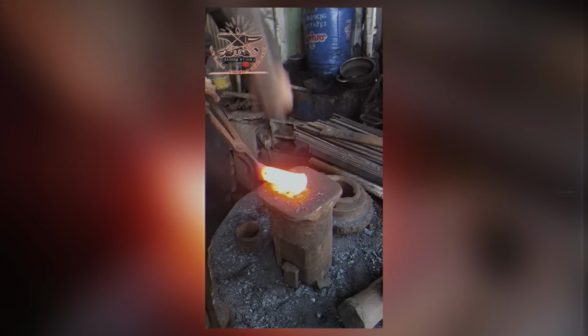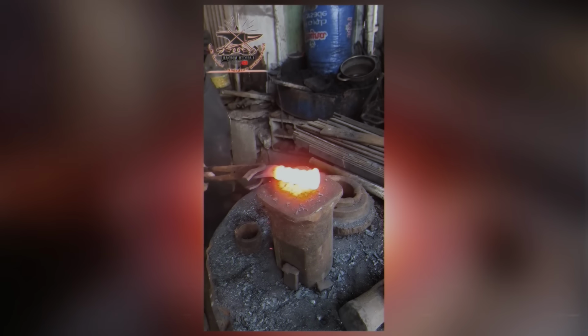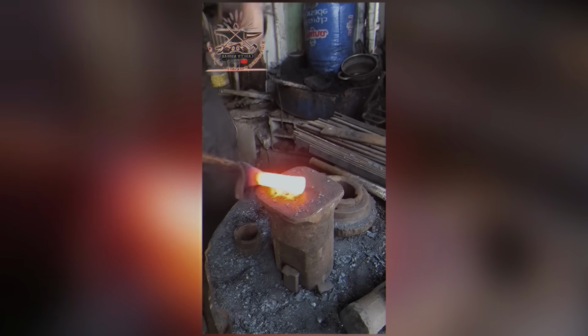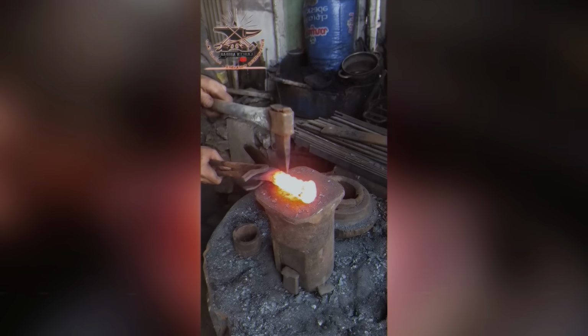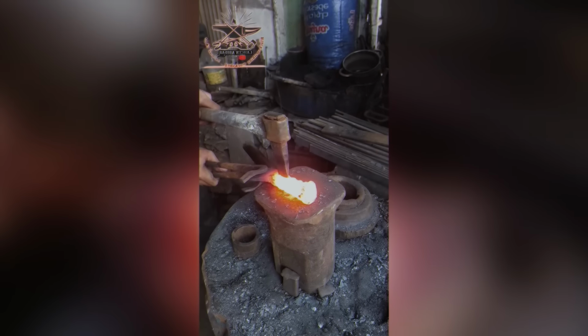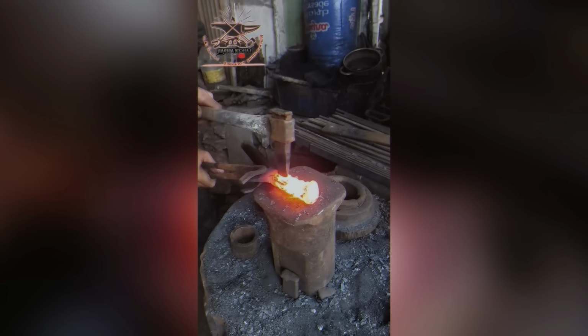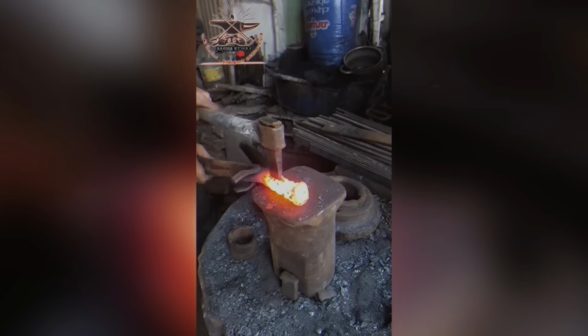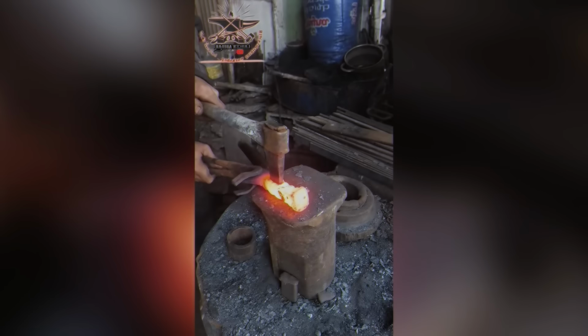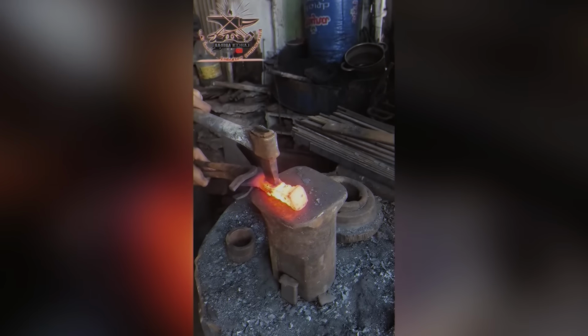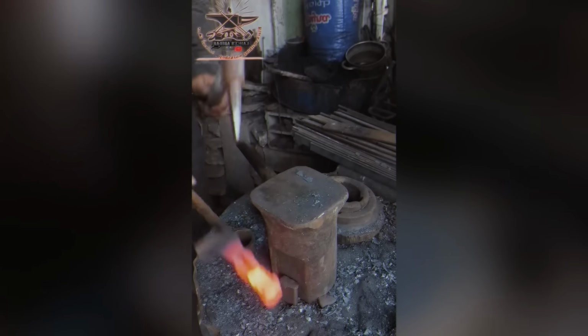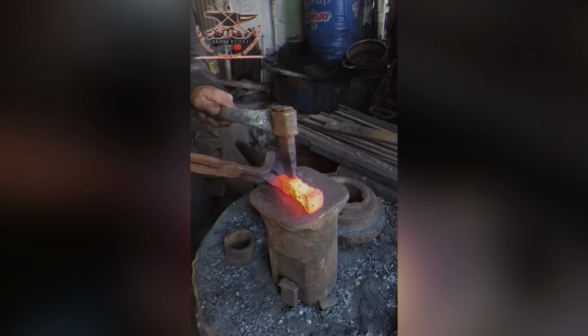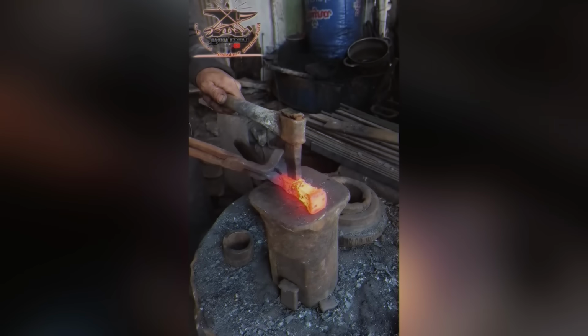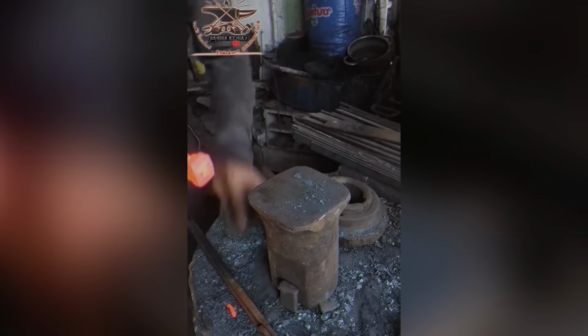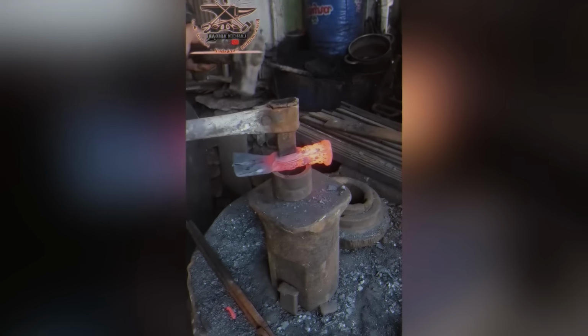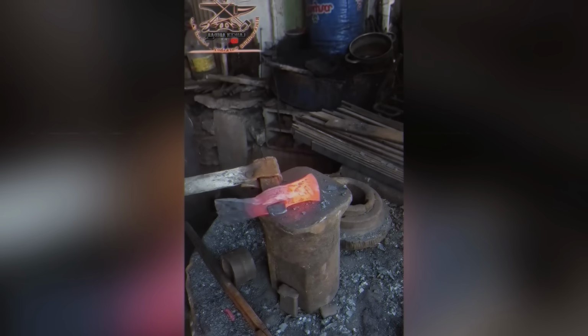The third sense was resistance feel. The blacksmith felt the resistance of the metal transmitted through the hammer. During strikes 1 through 30, resistance is high. The metal is too cold. It pushes back hard. Time to reheat. During strikes 31 through 100, resistance is optimal. The metal flows under the hammer but still provides feedback. You can feel the grain structure collapsing, reorganizing. This is the zone of maximum productivity. During strikes 101 through 150, resistance decreases. The metal is becoming too soft.